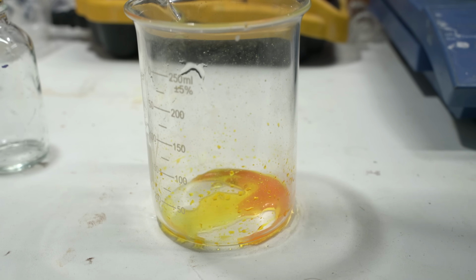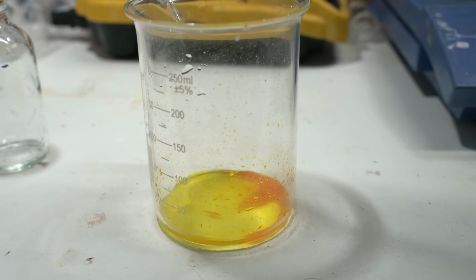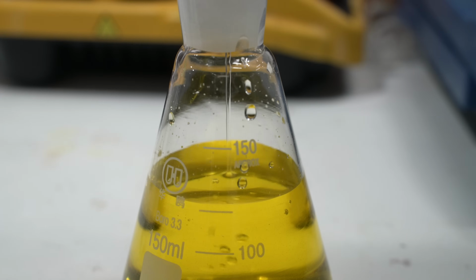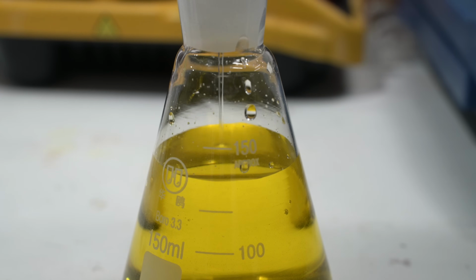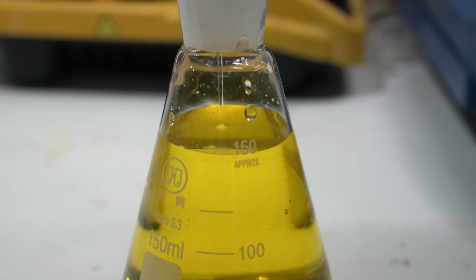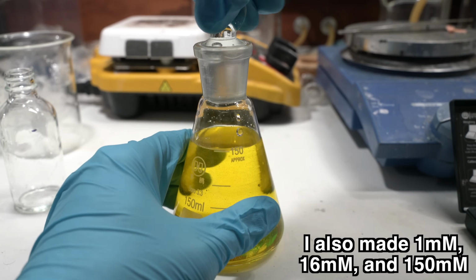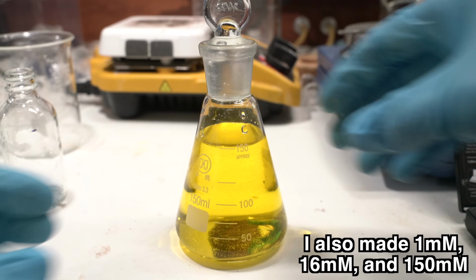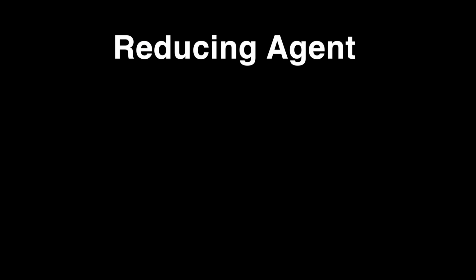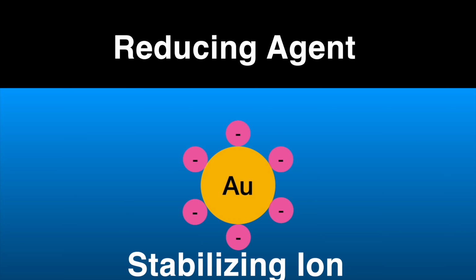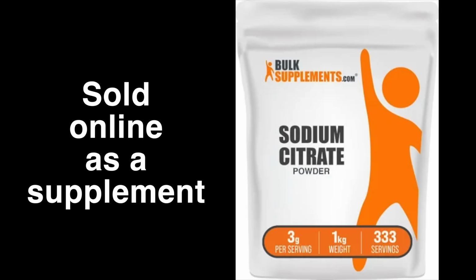Now that I had pure chloroauric acid, I could add distilled water to it and make a solution. I added just enough water to make a 33 millimolar solution. From the papers I read, this solution should be more than sufficient to make nanoparticles. Lastly, we need a reducing agent, and an ion for stabilizing the gold particles. The most common reducing agent for making gold nanoparticles is sodium citrate. The citrate can pull double duty as both the reducing agent and the ion to stabilize the gold particles.